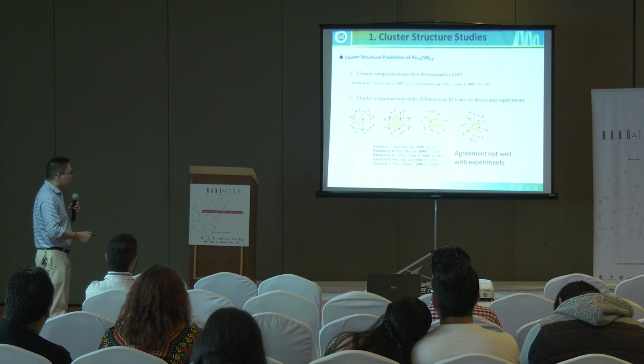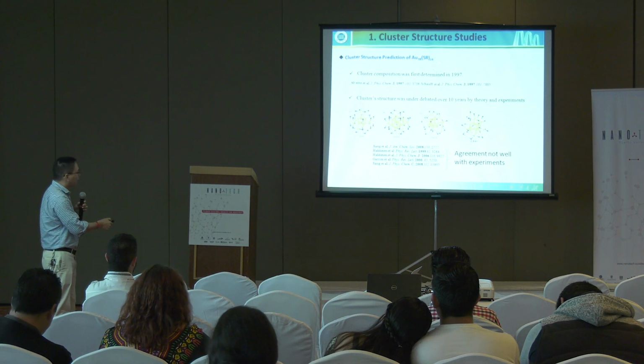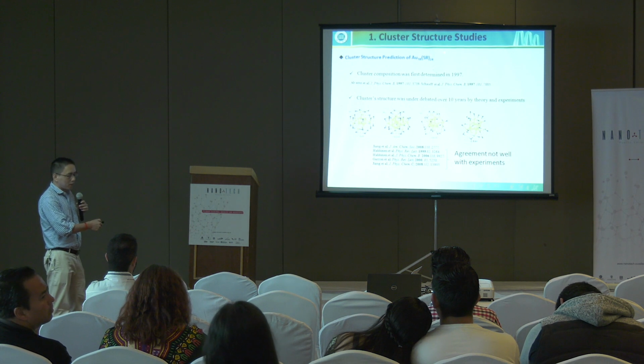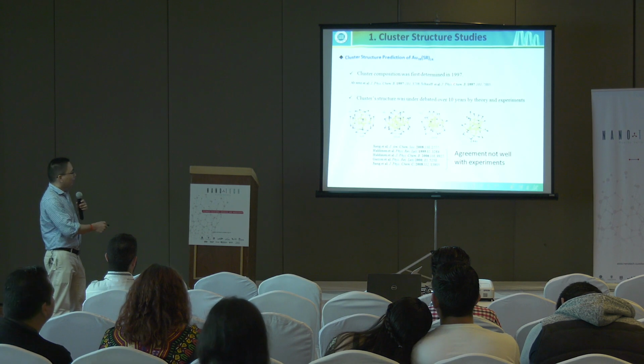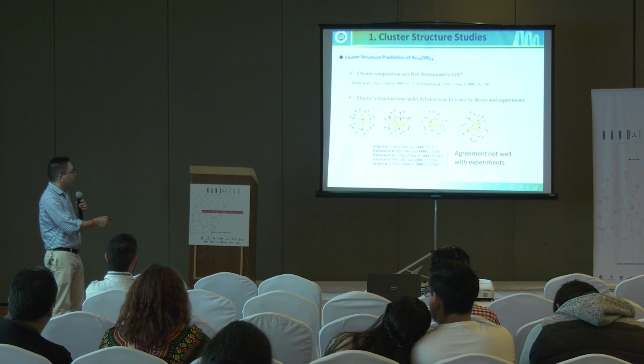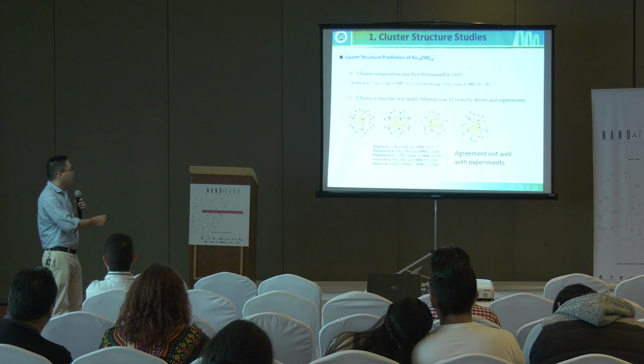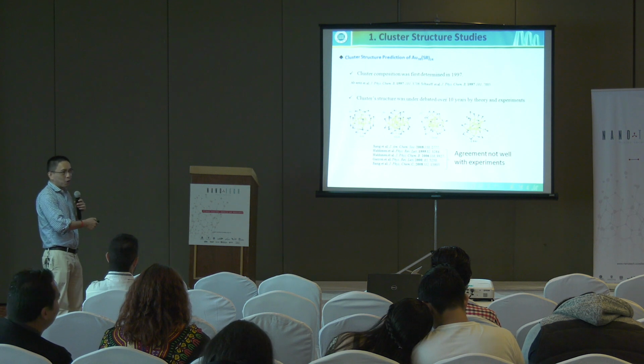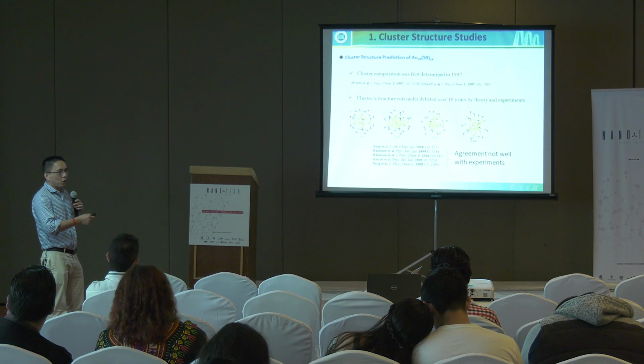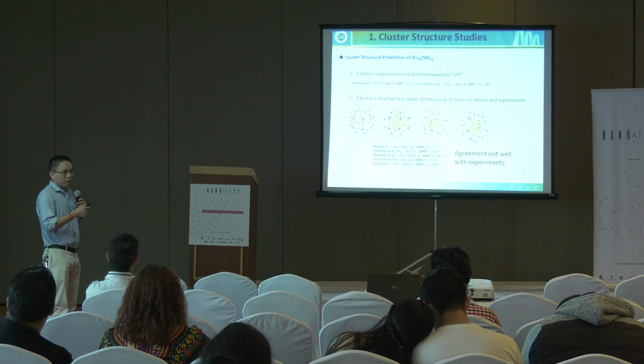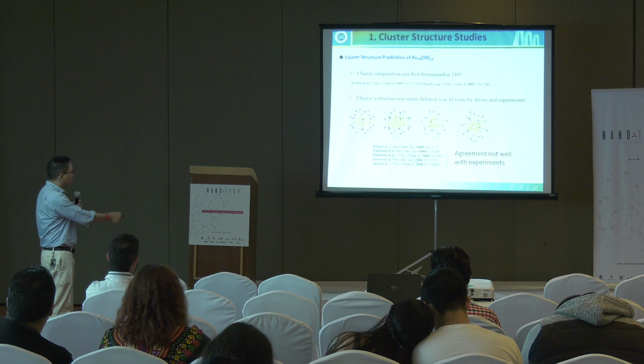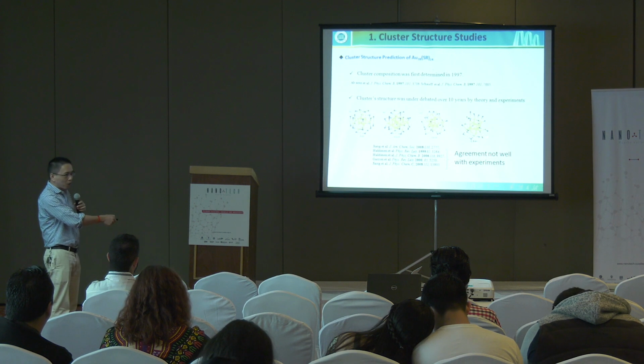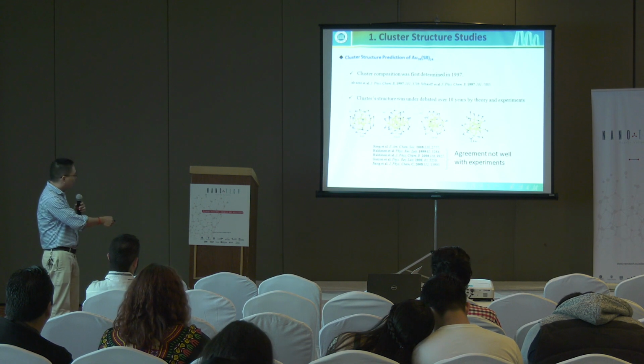This is the first example where we used this method. This is about the structure prediction of gold 38. Gold 38 is a famous cluster in this field. It was first synthesized in 1999. However, even after 10 years, the structure was totally unknown from both experiments and theory. And there are several theoretical works to search its structures. One work was from Professor Gallup in 2000.